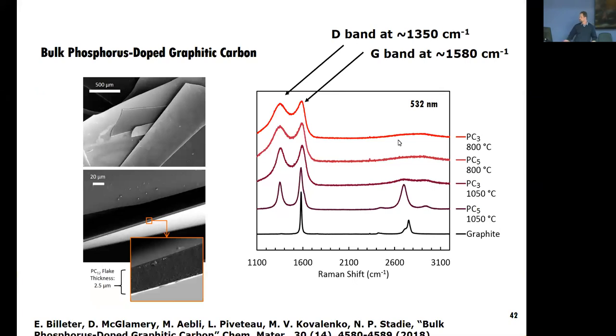So what they did is they had different stoichiometries of carbon and phosphorus. And what you see here is, so PC3 and PC5 are different stoichiometries. And then you see the temperatures here. And what you see is that in this stoichiometry at 1050 treatment, 1050 degrees Celsius, you have more of a graphitic character, but you still have this D band that might be desirable or not.